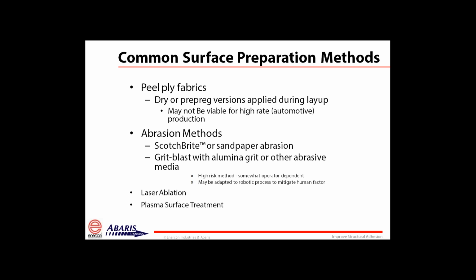And in some cases, you do see that you get a better, lower contact angle, and better surface free energy values, higher strength end result. In other methods, or using the same method with a different operator, you may find different results. So abrasion is very dependent upon operation. Scotch-Brite, or the nylon abrasive type soft materials, work quite well if used with a tool that runs at a low RPM or by hand. And the same thing with sandpaper abrasion. Grit blasting is another option, generally with alumina grit or other abrasive media that is sharp and works well.